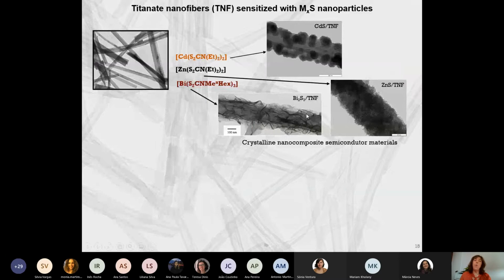Another example is, why not try to modify this titanate nanostructure with a second phase, a second semiconductor phase? Here we decided to study metal sulfide nanoparticles. We have used single source precursors. And as you can see, we are able to prepare different materials with different morphologies. In this case, we have nanocrystallites of zinc sulfide. In this case, they are also very, very small nanocrystallites, but these are islands of small crystallites. And here we have a kind of sheets surrounding the fiber, because bismuth sulfide is a laminar semiconductor.